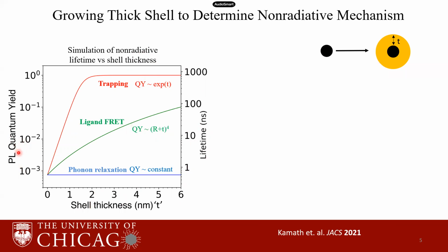Over here, I have the simulation for the PL quantum yield as a function of the shell thickness. The PL quantum yield is a direct proxy for the non-radiative lifetime, and it is a useful quantity because it is easy to measure experimentally.